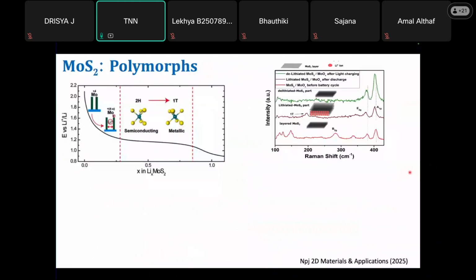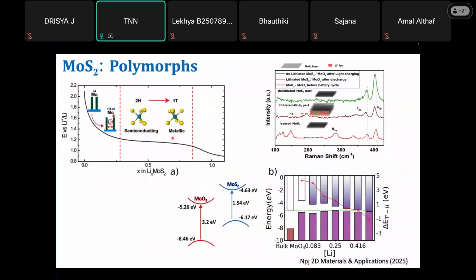Now another fundamental question comes here. As I mentioned, when it gets intercalated with lithium, phase transition can happen. In one of the earlier slides I mentioned, a slight strain in the sulfur plane can transform a semiconducting MoS2 to metallic MoS2. And as I told you, spectroscopically using Raman, you can see that particular phase formation. And when you charge it, reversibly that phase disappears and it goes back to the other phase. Now the question is, in MoS2, a small amount of lithium itself will metallize the MoS2. If it becomes metallic, then there won't be any more exciton formation.